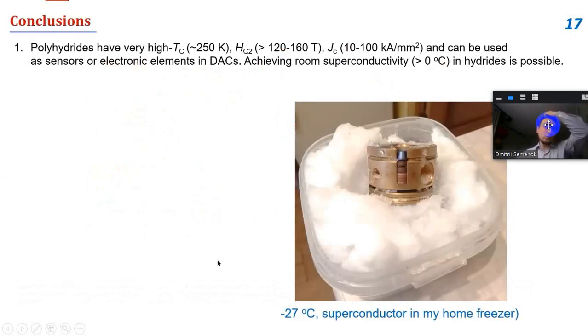Okay. And so finally, I would like to underline several conclusions. So polyhydrides have very high TC. It's a new class of superconducting materials, which has much better characteristics than all other superconductors discovered in the last 100 years. Polyhydrides have a TC up to 250 kelvins now, and the critical magnetic field is above 120, 160 Tesla. So we cannot destroy superconductivity. We cannot suppress superconductivity using the magnetic fields available on Earth.